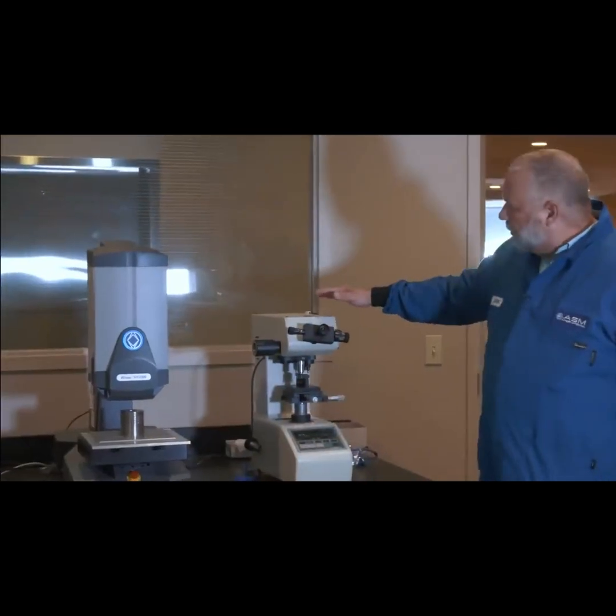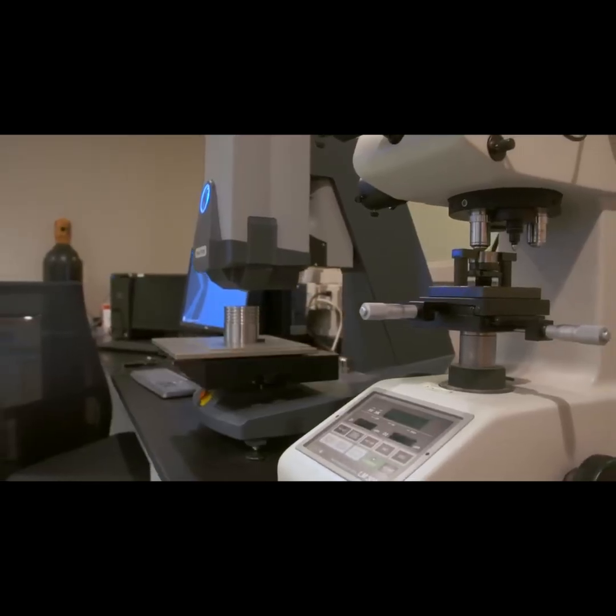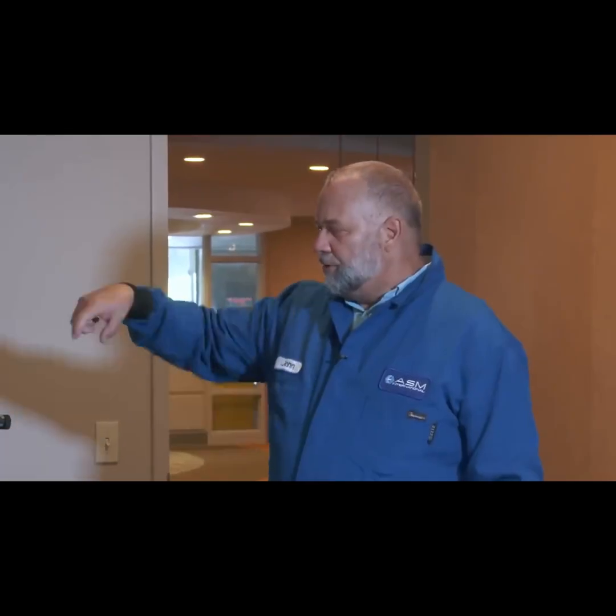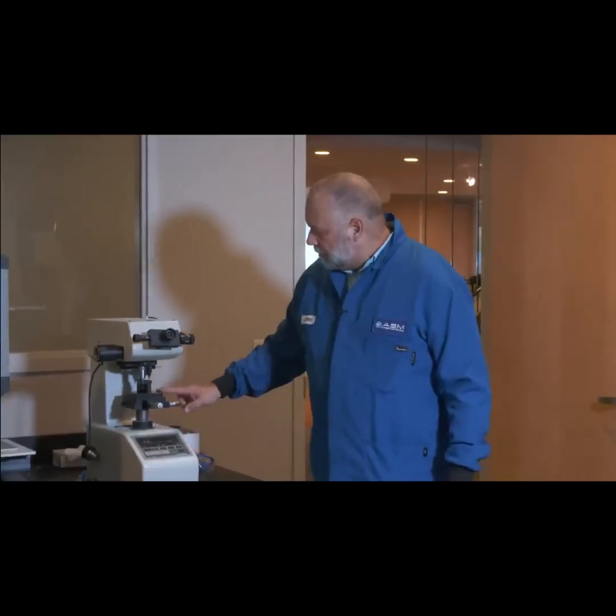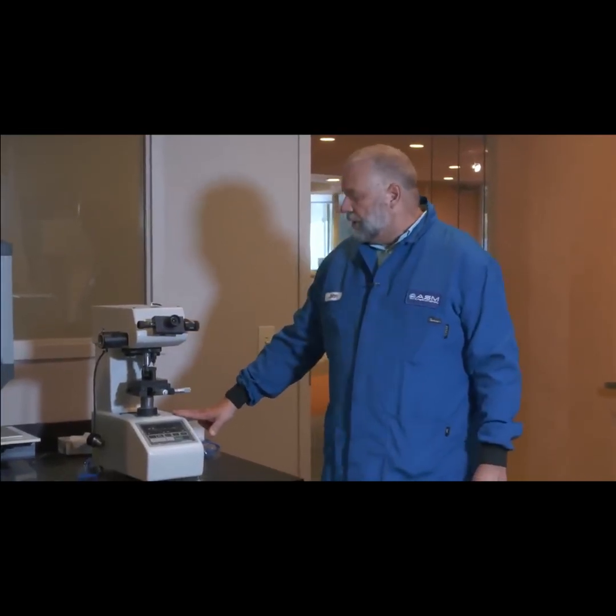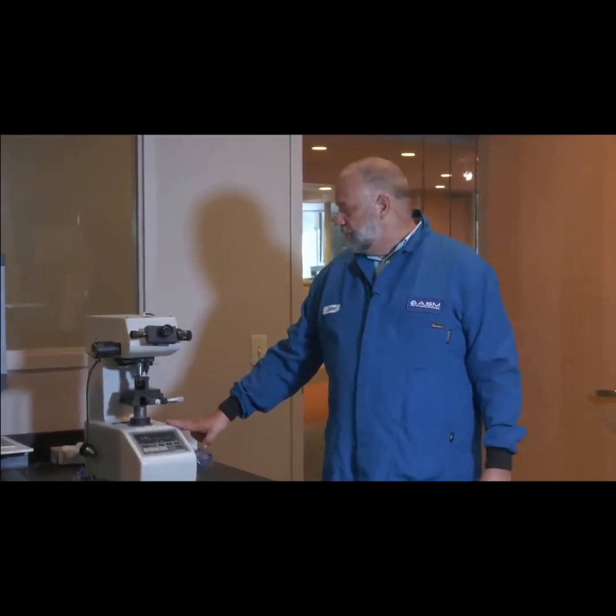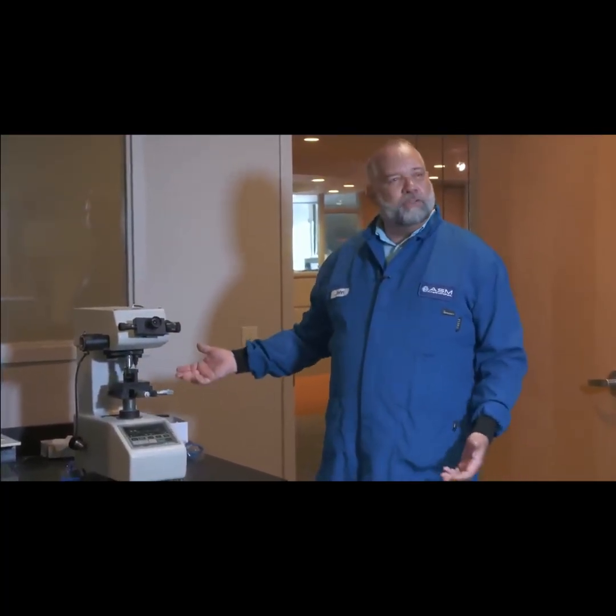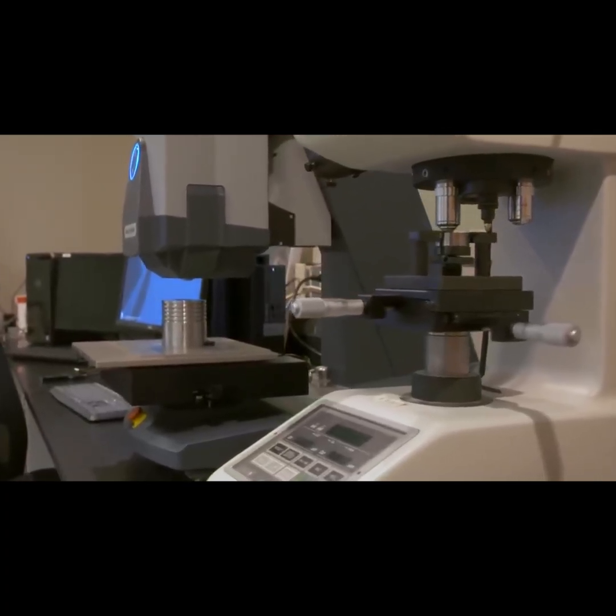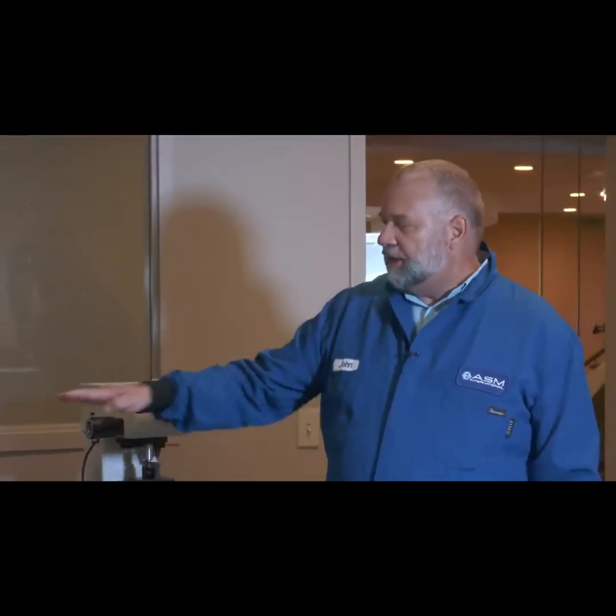And this is a microhardness tester that is very manual. You measure in the eyepiece the shape of the dimensions, and normally one or two diagonals, and then you bring it down, and then you have to dwell for 10 seconds or so. So every indentation takes about 20 to 30 seconds. So now that you have automation of a fully motorized stage, a camera that measures the indentation, and a stage that can lay down predefined patterns, you can do hundreds of indentations.